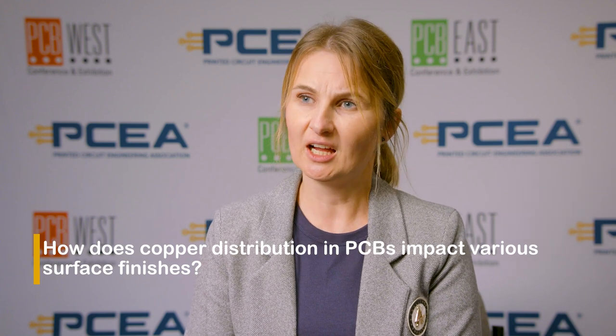So copper distribution can impact surface finishes very significantly. It's going to affect the thickness of the layers, it's going to affect the adhesion to the surface, and then overall it's going to have an influence on the functionality of the board. For instance, copper distribution is going to affect the distribution of the current densities during the electroplating process, creating high and low current density surface areas that are going to have a direct impact on the thicknesses in those places.